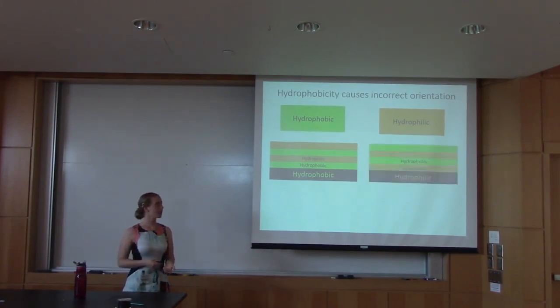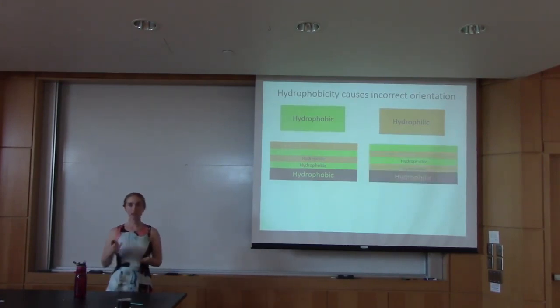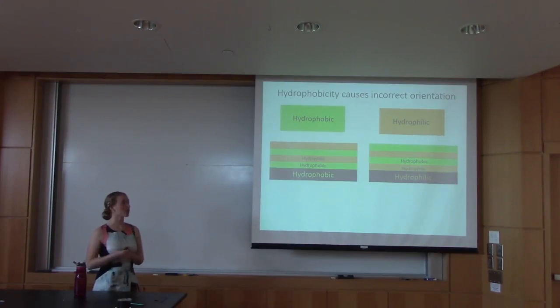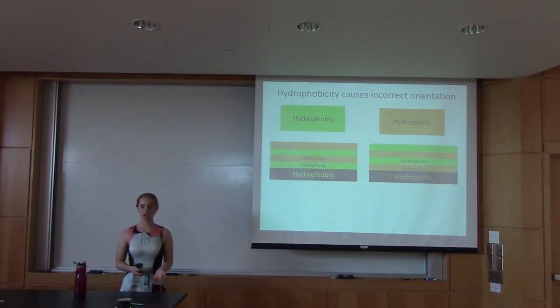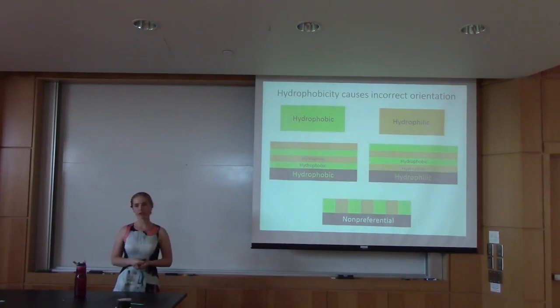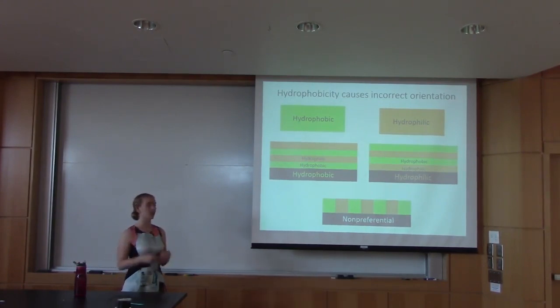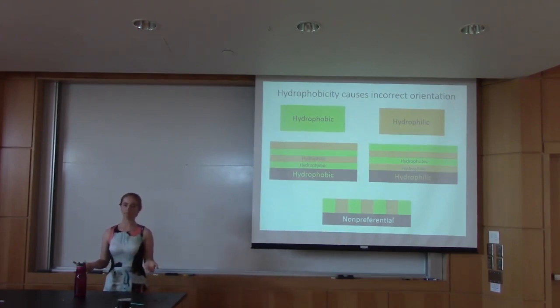On the other hand, if we have a hydrophilic surface, the opposite is going to happen. The orange part, or the hydrophilic part of the block copolymer, is going to orient itself closest to the hydrophilic surface. And so in order to avoid this parallel orientation, we need a non-preferential surface. We need a surface that is neither hydrophobic nor hydrophilic in order for there not to be any preferentiality in the way that the block copolymer orients itself, and thus we achieve a perpendicular orientation.